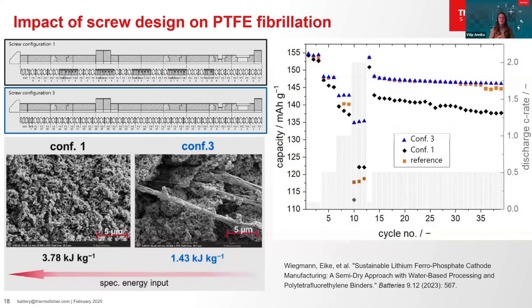However, now let's examine the cycling capacity of half cells made from these materials compared to a wet cathode mix in a planetary mixer as a reference, shown in the graph on the right. The cathode mix without kneading blocks in blue exhibits the highest capacity at all cycling rates over 40 cycles. The cathode mix with 5 kneading blocks in black has the lowest capacity and cycling stability. This study suggests that the PTFE fibrils in the strongly sheared sample isolate the conductive pathways leading to inactivation of the LFP. This highlights the importance of tailoring the screw design to provide the right energy input for the specific PTFE grade. And this brings us to the summary of the presentation on twin screw mixing for processing dry electrodes.